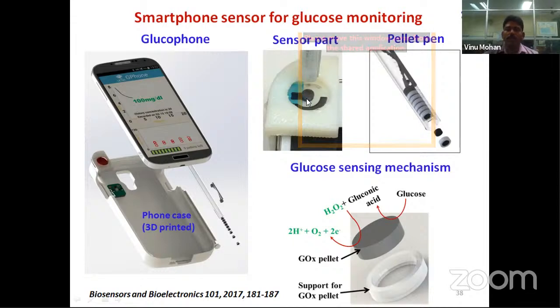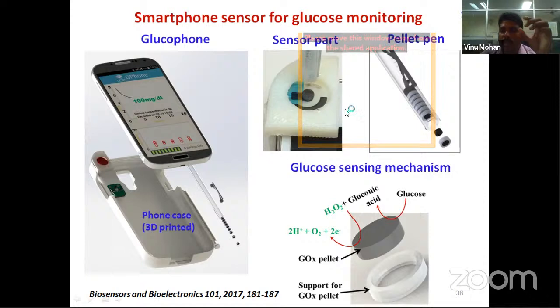You can see the 3 electrode system, and we developed a PCB for controlling the sensor, which is powered by the phone battery itself. One added advantage here is that the sensor can be used multiple times. Every time there is no need to remove the flexible or disposable sensor; we can just replace the active layer. Here we prepared the active layer in the form of pellets. You can see a 3D printed pen is available, filled with several pellets. Inside the pellet, we loaded the active materials.